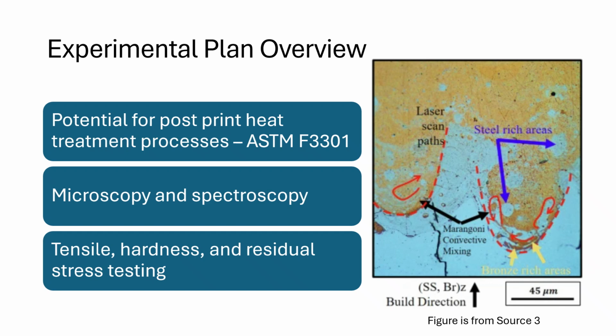Hardness will be covered with micro-hardness tests following ASTM E384. This standard is specifically written for hardness over short distances, which will be useful for capturing how the material changes as the mix of powders changes. To get interfacial integrity, I will use 3D X-ray computed tomography and a focused ion beam method to cross-section the printed parts for analysis. Finally, I will benchmark the residual stresses by following ASTM E837.